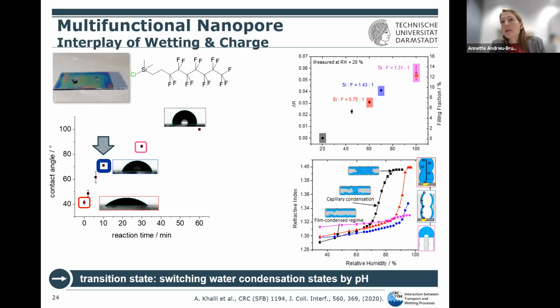This is then the data on the pore filling, which shows you that you have up to 13 volume% pore filling, but still this result cannot be explained by the pores being fully filled. So there's still the majority of pore volume accessible.